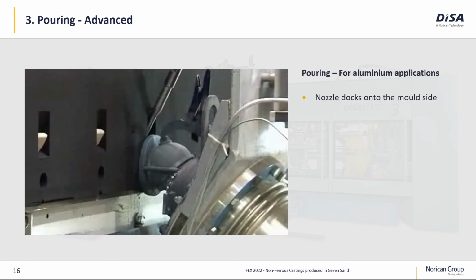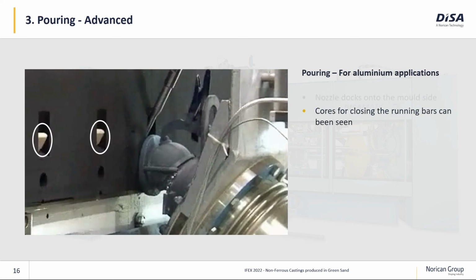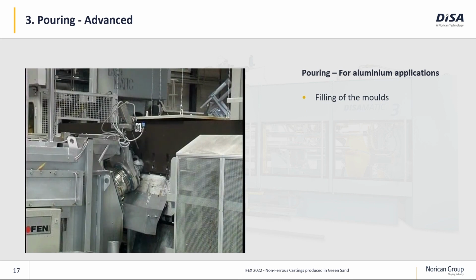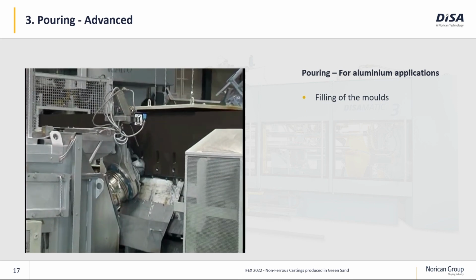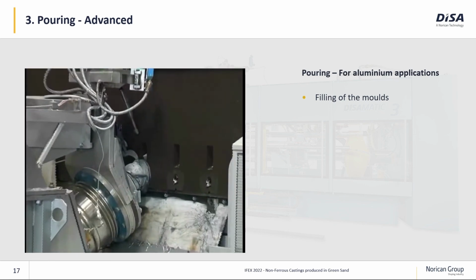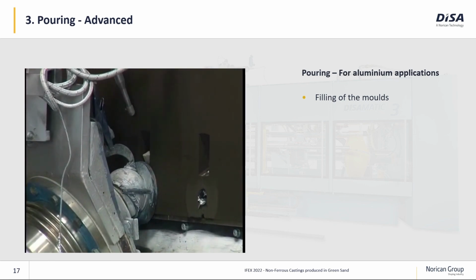And how does that look in real life? Here we see the mold. We see the nozzle on the pouring device docking to the side of the mold, and we see these small cores we use to block the runner bar when the mold filling is over. This is how it looks in real life. We do mold transport, we dock to the side of the mold, then gently we fill the metal into the mold, and when the mold is completely filled, we close the runner bar with this small pneumatic cylinder pushing the core into the runner bar. We can move away, do mold transport, and then pour the next mold.